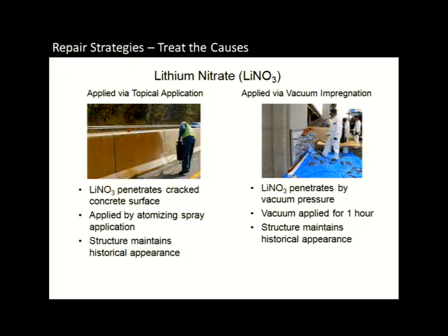We had some concerns, though, about how effective that would be if you can't drive the lithium nitrate deep within the structure where all of this reaction is going on. So we also did some work with vacuum impregnation, where you basically apply a vacuum pressure to the top surface of the concrete and you pull the lithium across and you try to drive it in that way.